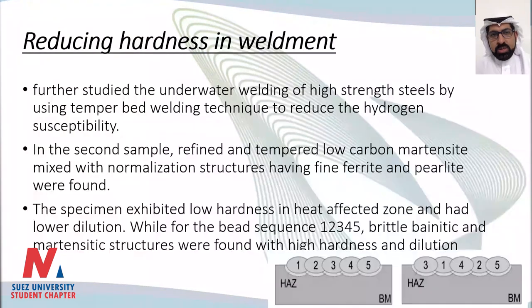Next, please. So to reduce hardness, these are some techniques that I found in a study about it, that they use a temper bead. Basically, you're using a sequence. If you're using a sequence, then you're making a more brittle material, so you're making bainite microstructure and martensite, so your material will be hard.